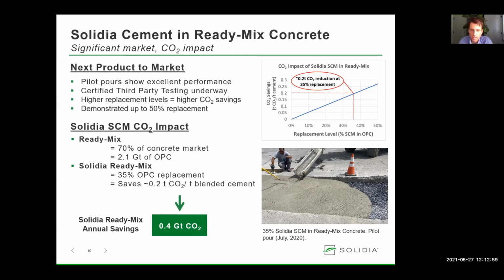The plot illustrates CO2 savings versus replacement level. Using the base case of 35% replacement level, CO2 footprint is reduced by 0.2 tons CO2 for every ton of blended OPC made with Solidia cement. Like precast concrete, the potential CO2 savings of Solidia SCM is large. Traditional ready mix represents 70% of the concrete market and consumes about 2.1 gigatons of clinker annually. Replacing 35% of the OPC cement used in ready mix with Solidia SCM would save up to 0.4 gigatons of CO2 annually.